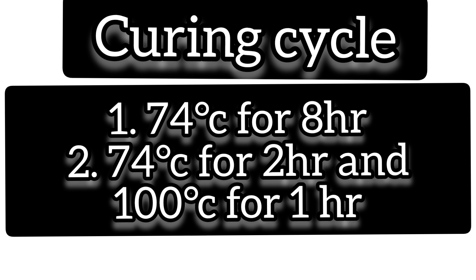The short curing cycle follows 74°C for two hours, then 100°C for one hour. This faster cycle is used when you need to deliver the denture to the patient as soon as possible.